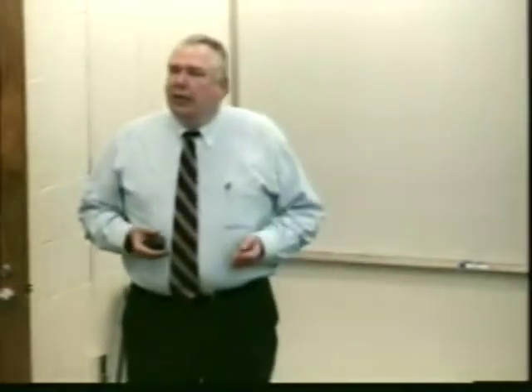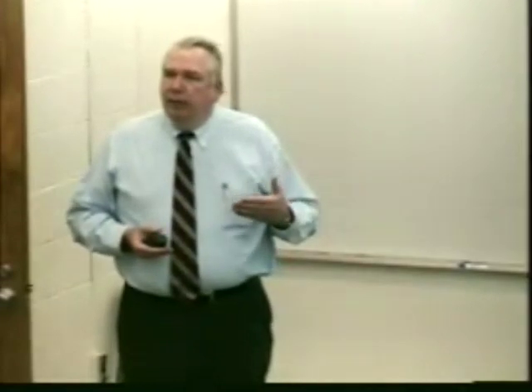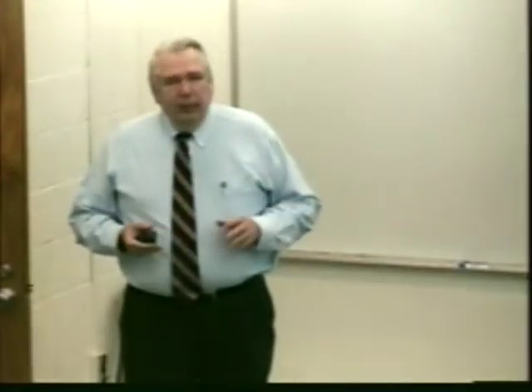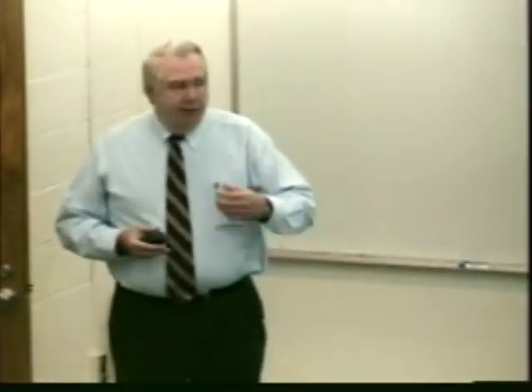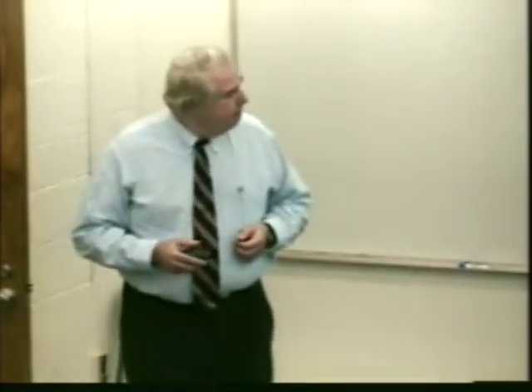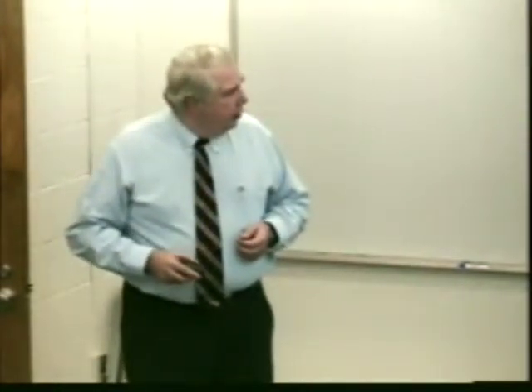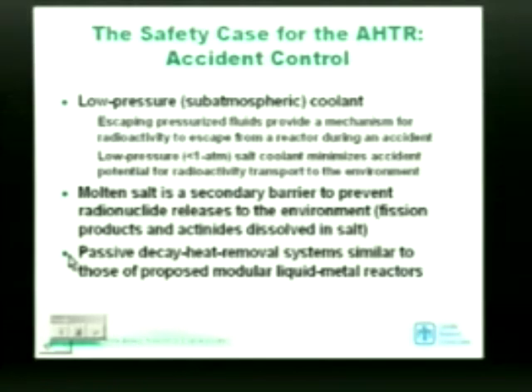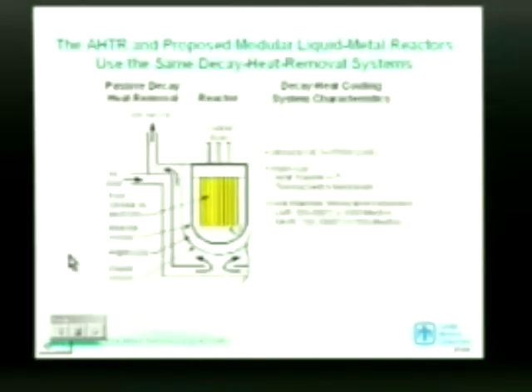But if fission products do escape from the fuel, we'll expect them to dissolve into the molten salt. So the molten salt acts as a secondary barrier to any releases from the fuel. Ideally, there's no releases from the fuel, but we have this secondary barrier. The third feature is that we can use passive decay heat systems similar to those proposed for the liquid metal reactor, in particular the S-prism.